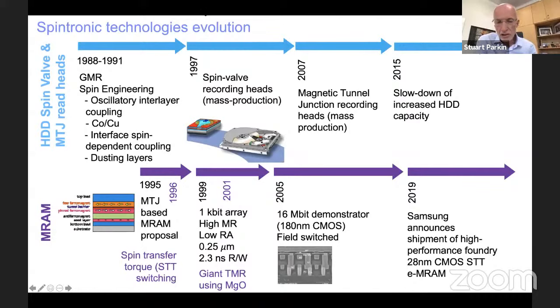And then the idea is, as I mentioned, we could use this to store information. We proposed this in 1995 when the magnetoresistance of these devices was only a few percent at room temperature. Within 3 years, we demonstrated 80% was possible, and we could reduce the resistance of the tunneling junction devices at that time by more than 100 million times to make it useful for a MRAM application. And we demonstrated that in 1999 with reading and writing speeds of just a few nanoseconds.